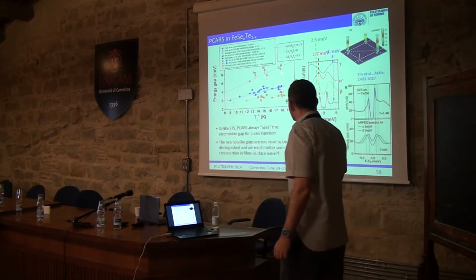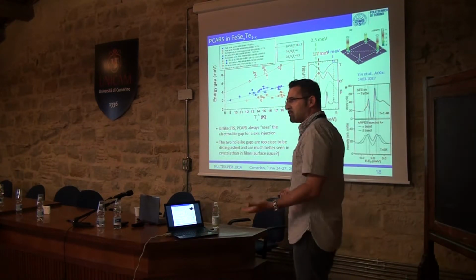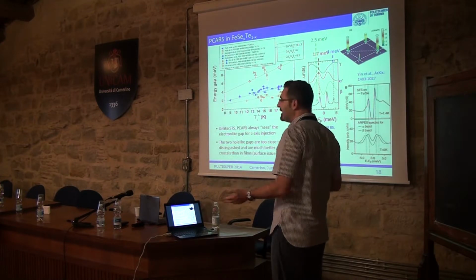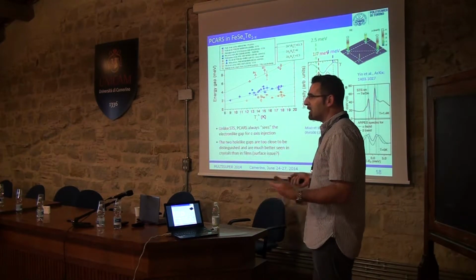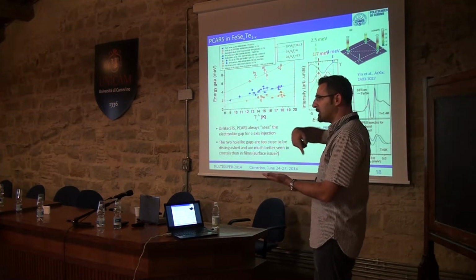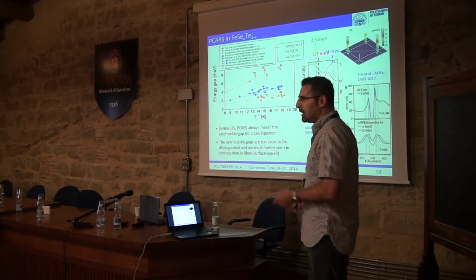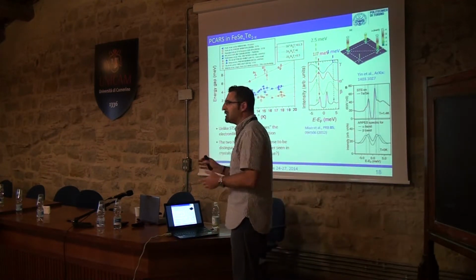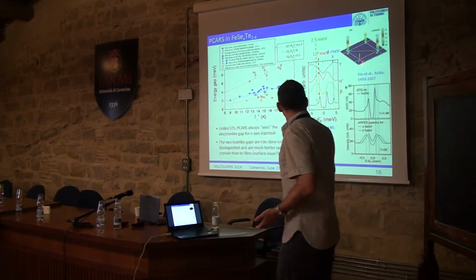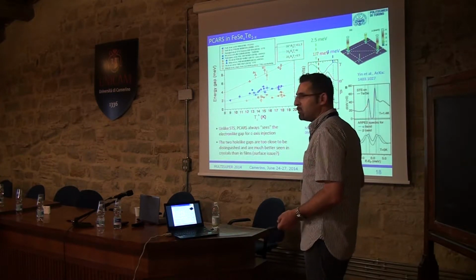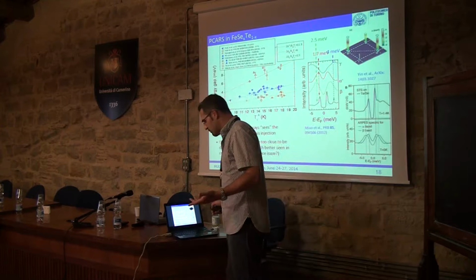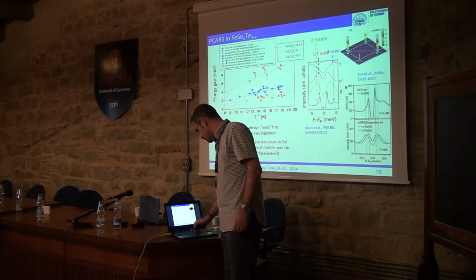By the way, all these fits have been done using isotropic gaps, so we do not have any clear evidence that the gap is anisotropic. The fourfold oscillations in the gap observed by angular dependent specific heat apparently do not appear, but neither do they appear in Andreev measurements. So the reason for this disagreement is not known to me.